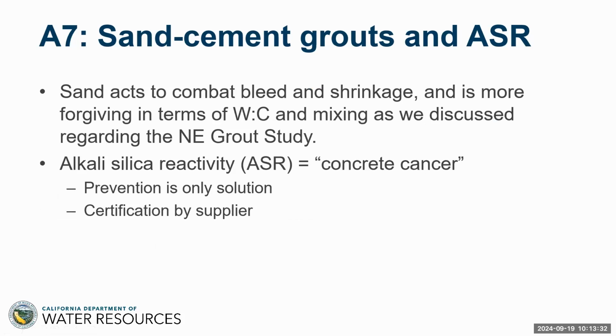Well, I'll be as brief as I can with this. So we know that when we put sand in the grout, it increases the internal friction. The sand typically doesn't react chemically, so it's purely a physical change that it's bringing about in the grout. And we use it to help combat bleed and shrinkage. And as we mentioned before, it's more forgiving in terms of variations in the water cement ratio. Also in terms of mixing, as you alluded to, Julie, the BNL tests produced a very good mix, the mix 111, and it performed adequately when mixed both in paddle mixers or colloidal mixers, although BNL did give the opinion that they preferred, for various reasons, to use the colloidal mixer.